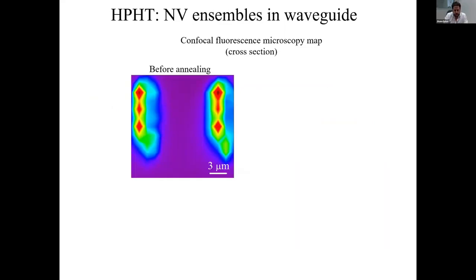And so what we did is we actually performed quite a bit of analysis, and we show before and after the annealing. So of course, before the annealing, what we found is this situation here. So again, this is confocal fluorescence microscopy, a cross-sectional view. Again, you see these elliptical sidewalls making up the waveguide. And we see strong emission from the actual damage lines because we're forming quite a bit of defects within these sidewalls, okay? So they're actually NV centers, we're writing in the sidewalls.